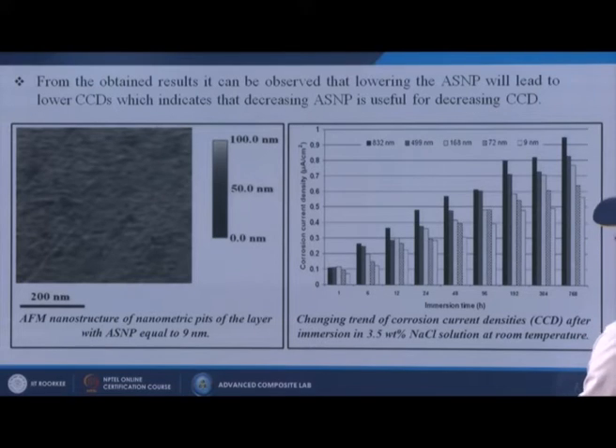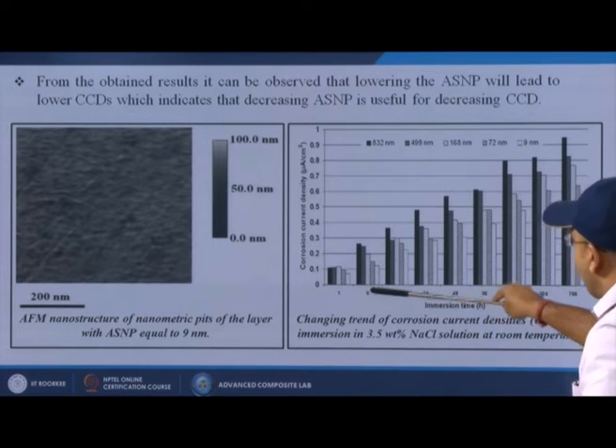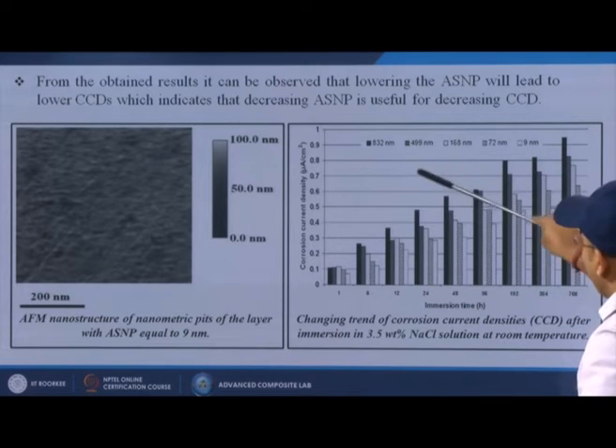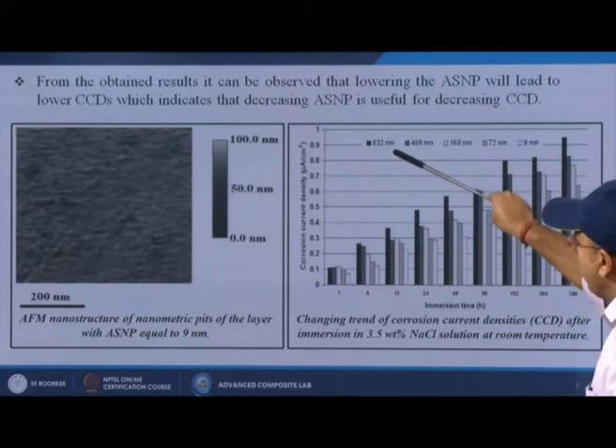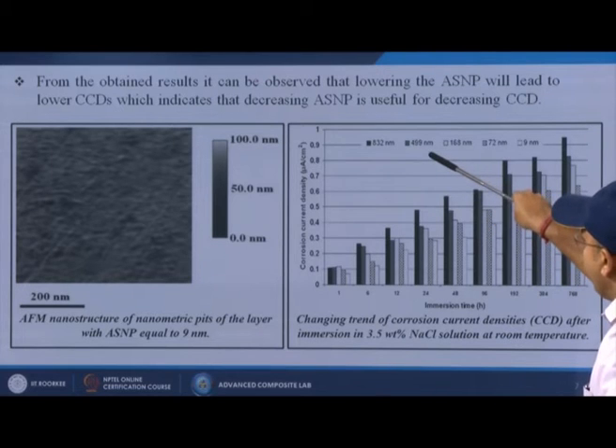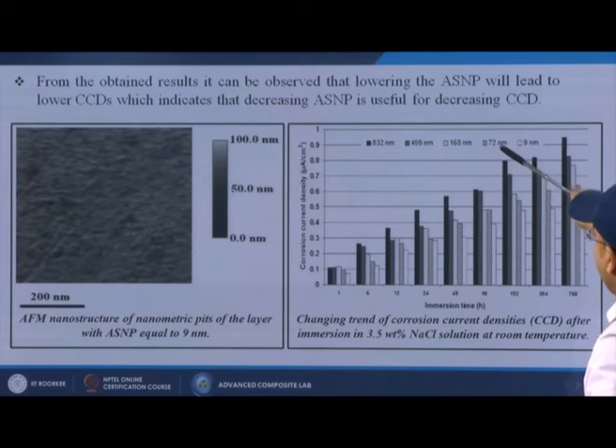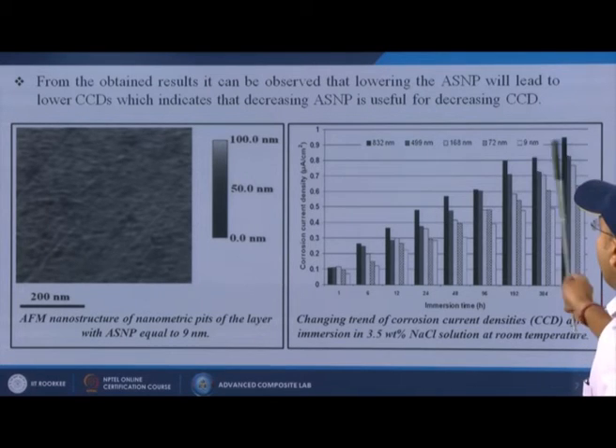And on the right hand side we have shown what the corrosion current density will be if we increase the immersion time, and not only that, we are changing the particle size also. So, first we are going for a smaller size, then slowly we are increasing the particle size, like that. The black one is giving you 832 nanometer, then 499 nanometer, 168 nanometer, 72 nanometer, 9 nanometer. So, when we look at the high immersion time, we can see that the corrosion current for a smaller particle size is much lower than the bigger one, that is the 832 nanometer particle size.